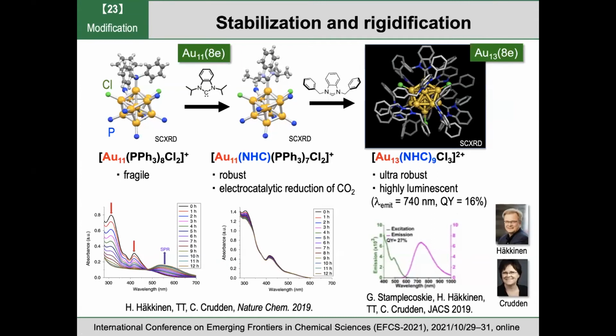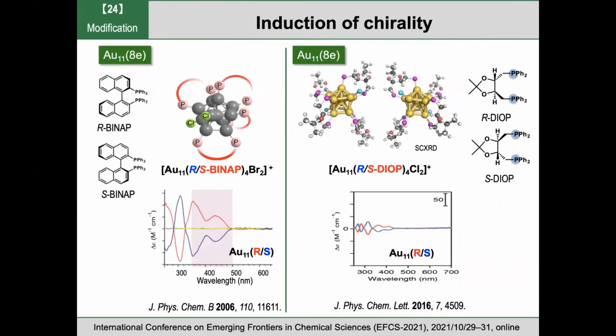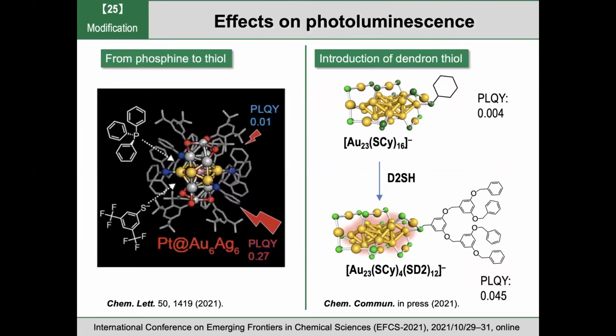And if we use chiral ligands, like BINAP and others, you can induce CD activity, chiroptical activity, because maybe the core is deformed into a chiral form by these chiral ligands. The photoluminescence quantum yield can also be enhanced by replacing the ligands. In this case, we replace the ligand with much bulkier ligands, while retaining the core structure, but the photoluminescence quantum yield is enhanced dramatically. We believe this is due to rigidification of the core by taking advantage of ligand-ligand interactions, such as van der Waals or pi-pi interactions. This kind of interaction can rigidify the core and suppress the non-radiative decay from the photoexcited state. So the ligands can tune the properties like this.